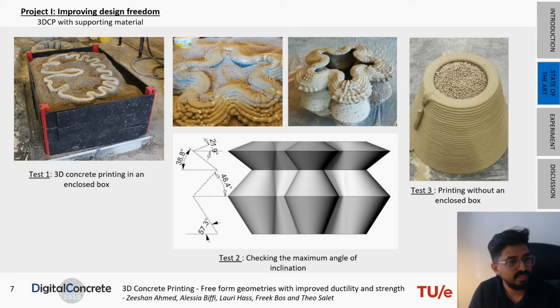We started this test by printing in an enclosed box, and simultaneously during the printing process, the lava grains were added. This showed significant proof of concept, and the project was a success. The next step was to check what degree of freedom we can achieve with this process. In the second test we checked the maximum angle of inclination, and during this test we realized the maximum angle of inclination which we should limit ourselves to during this process is around 35 to 38 degrees. To make this process more efficient, we have also tested this process without an enclosing box.